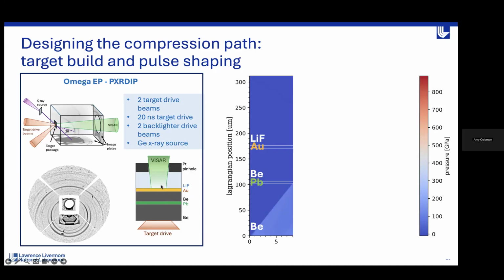Then we have our sample that we're interested in and our LiF window at the back - this is where our VISAR comes through. The other thing to point out, which will become relevant later, is that on the back of our targets we also have this platinum pinhole. This is a layer that is not compressed - this is ambient platinum, and it appears in the diffraction as such.